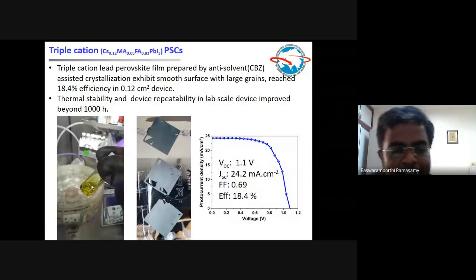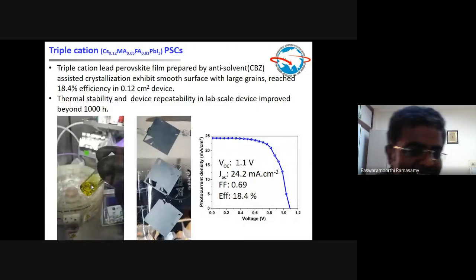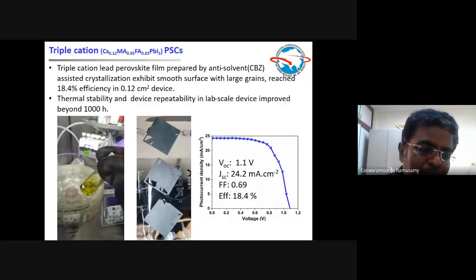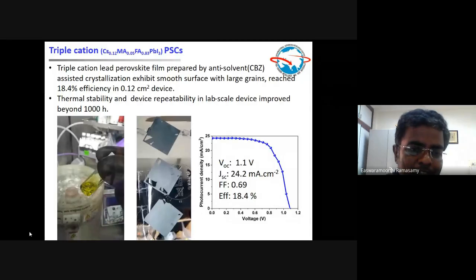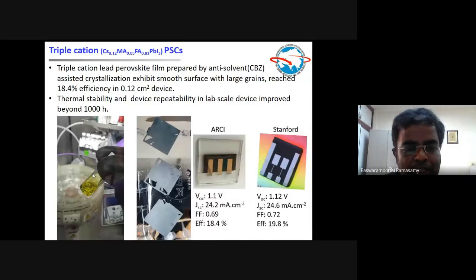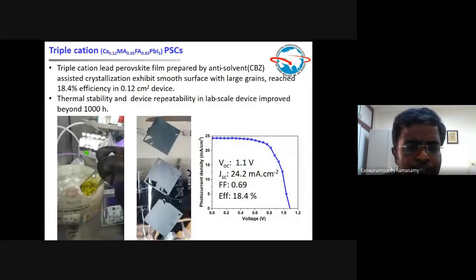How do you prepare that? Take the solvent DMF and put in lead iodide, methylammonium iodide. Simply you mix it, and then you will get a completely dissolved precursor solution. This is that solution, and this solution can be made into thin film form by spin coating. These are all the substrates with the perovskite thin film.